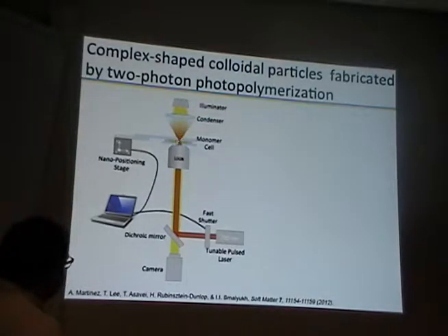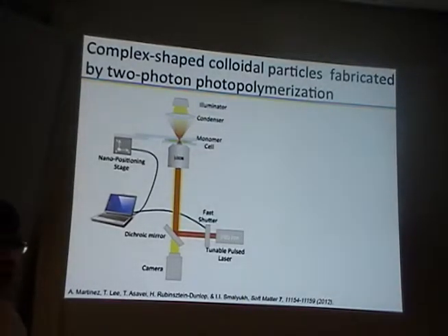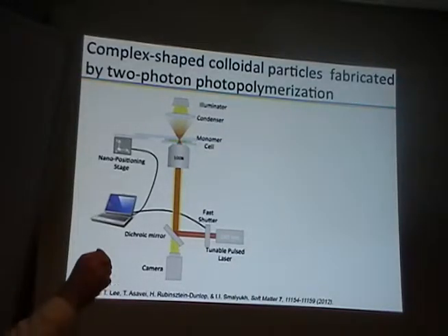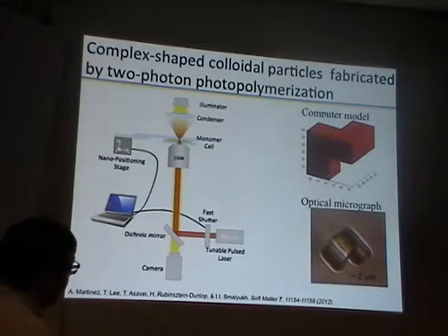Right? So this happens because we initiate the polymerization by means of two-photon absorption. Right? So photoinitiators are essentially dyes, and they can be activated not only by means of single photon absorption, but also two-photon absorption. And so as we do it, we cross-link the material, essentially converted from fluid to solid in the desired location, and then we scan the laser beam through the sample by drawing any structures we want. Right? And so an example you can see here.